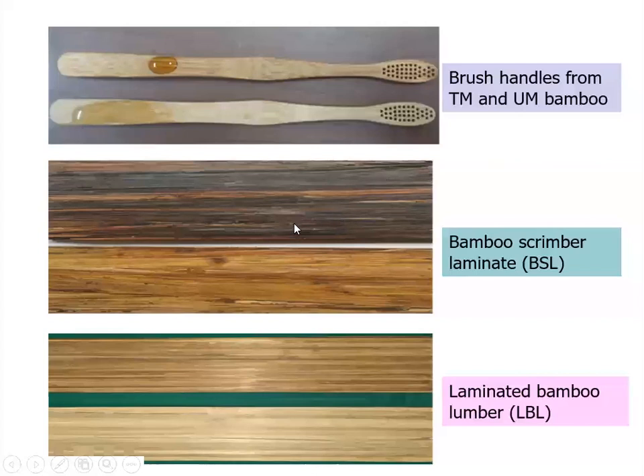Here we are not going to lose any amount of bamboo while converting. The full bamboo can be used for different applications. It is possible to produce crack-free flat bamboo boards with excellent mechanical properties, as an industrially scalable process, and the material can be used for composite production, and the adhesive requirement can also be reduced significantly.